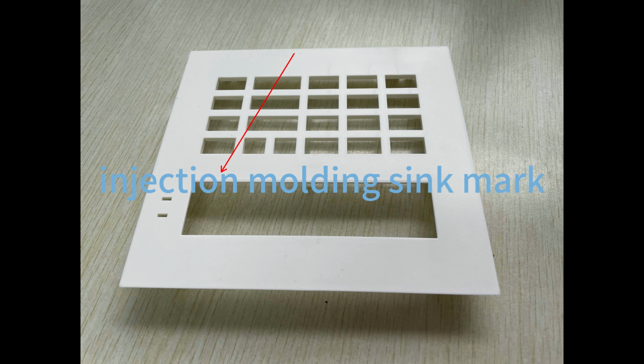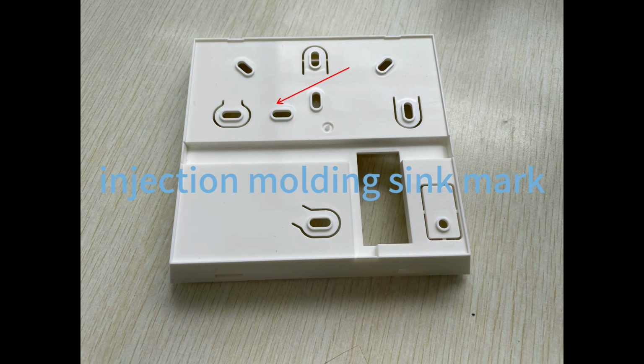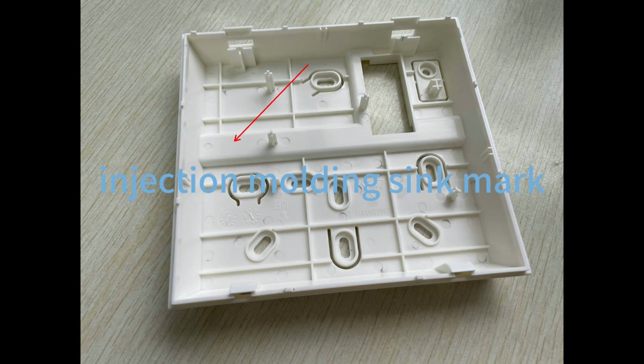Corrective actions for existing sink marks. Increase holding pressure and time. Reduce melt temperature. Extend cooling time. Modify part design to reduce wall thickness or add coring. Adjust gate size or location.